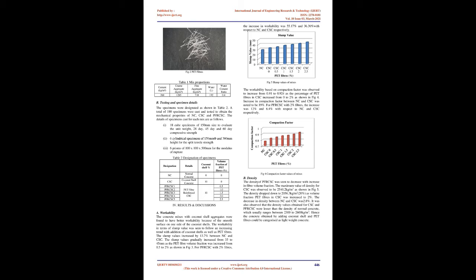Locally available coconut shells were crushed and sieved to get coarse particles with effective size of 15 to 20 mm and bulk density 1.69 g/cc, as shown in Fig. 1. The natural coarse aggregates were replaced at a volume fraction of 10% with coconut shell, and polythene fibers obtained from polythene bottles were added at volume fractions of 0, 0.5, 1, 1.5, 2, and 2.5%. The coconut shell content was restricted to 10% by volume of coarse aggregates, as the optimum value of coconut shell content for desirable compressive strength for the mix was found to be 10% from past literature 7, 12, 13.